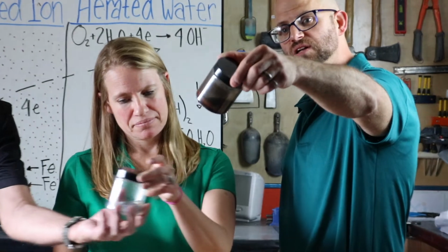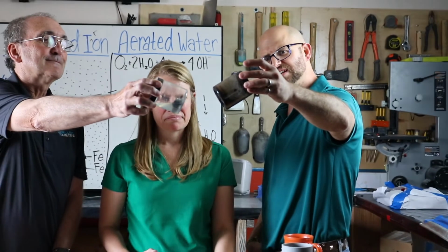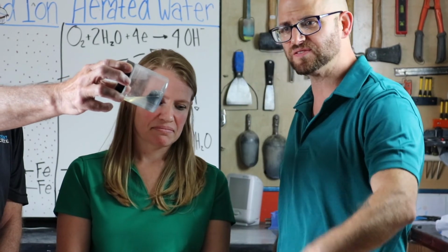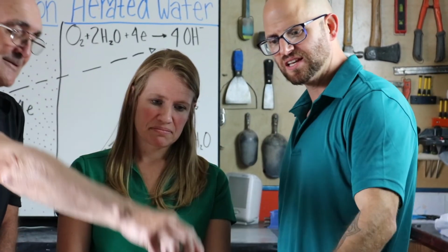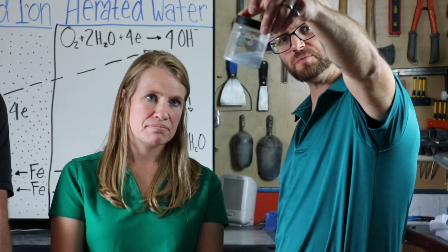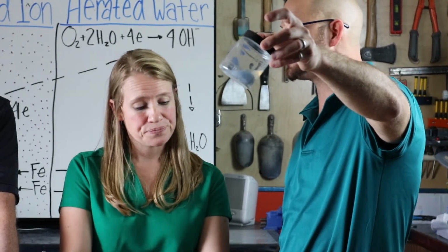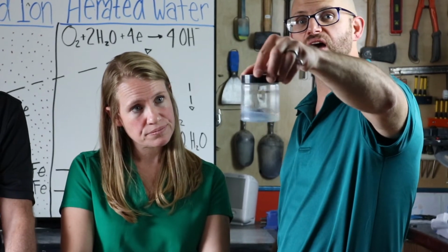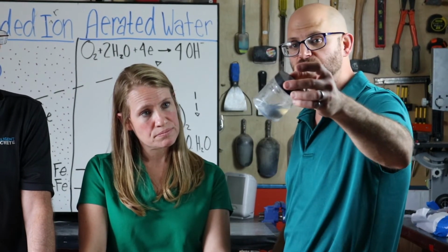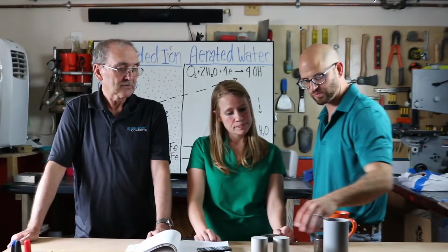So this was steel wool, and this started rusting after about 2 or 3 hours, and we put this in about 6 months ago. So the reaction is basically done. There's no steel wool left. This is one of our clients' admixtures. This is Crete Shield by Obex. It's one of their integral admixtures. And this steel wool has been in solution for 6 months now. We put it in the same day. And this is another way of attacking that steel reinforcement using new and emerging, now enhanced admixtures to make that steel reinforcement last longer. Absolutely. Make that concrete stronger and denser and what have you.